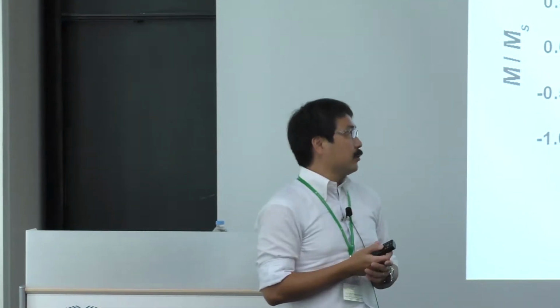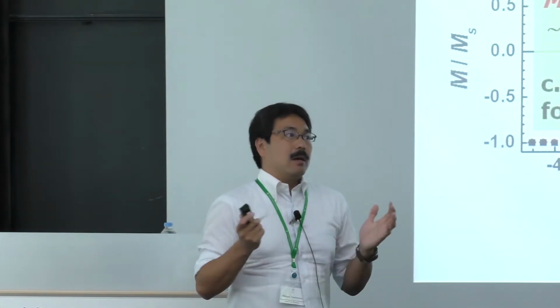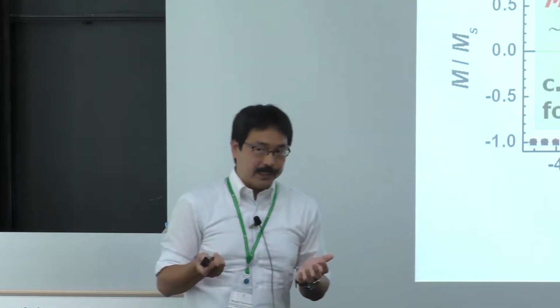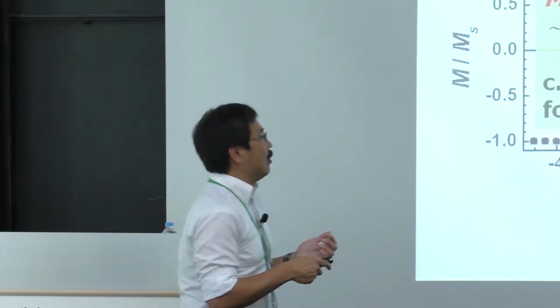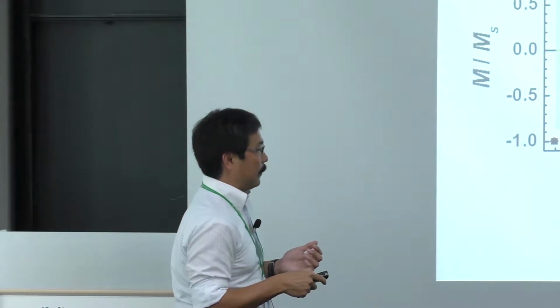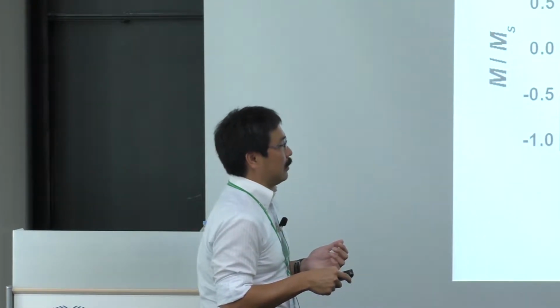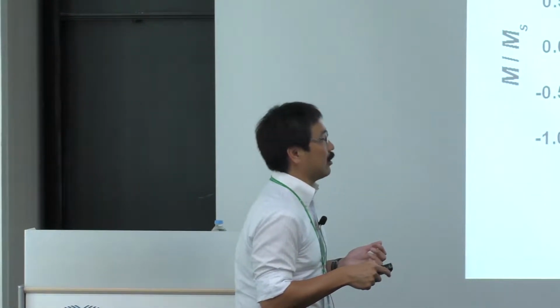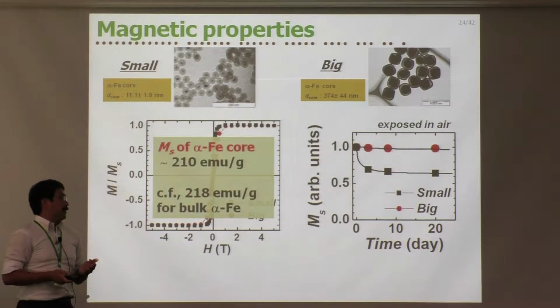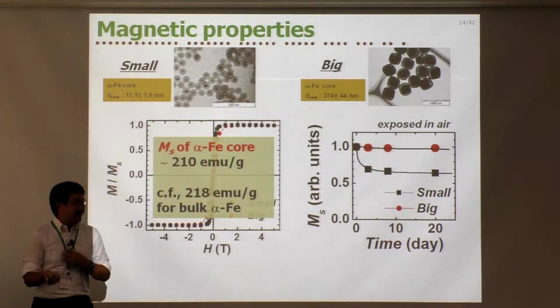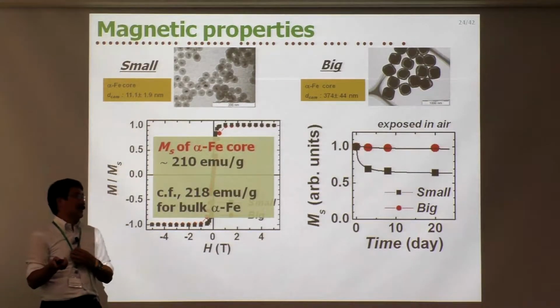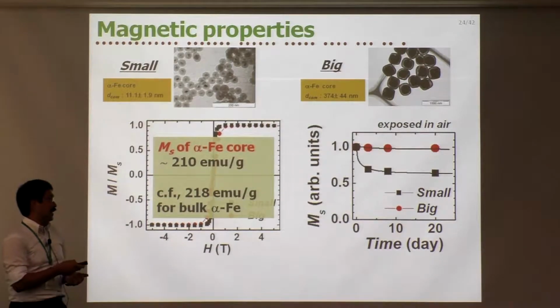So the problem is the degree of oxidization. For the case of the small sample, it still has more than 60% of the initial value. Even if I stress that this sample has more than 60% of its initial value, they are still oxidized.